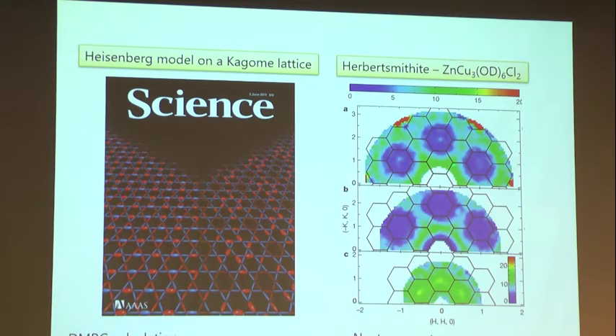And what they observed, as you can see here, where the hexagons are Brillouin zone boundaries, is that there are these excitations that spill over many Brillouin zones, which is very broad and has a unique shape to it. So this is an example of spinon excitations found in two dimensions. This presents one of the better known examples of quantum spin liquid in real materials. But this is kind of a one-off thing. This is an extremely difficult material to grow, and disorder always comes into play, so it is very difficult to replicate this success in many different materials.